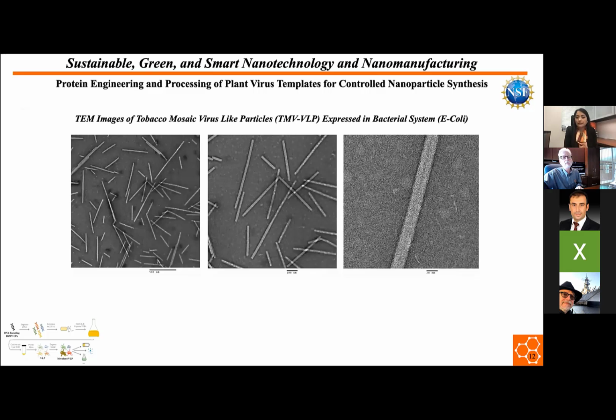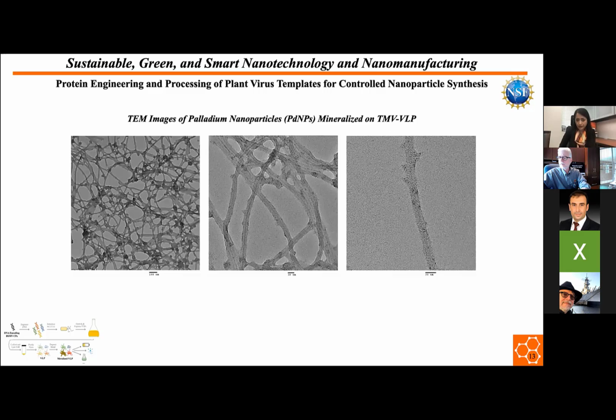I'm going to share some of the results that we got so far about TMV virus-like particles that have been expressed in a bacterial system and purified. As you can see in the TEM image, we got really nice VLP nanostructures without any aggregates or any other structures. And we used these virus-like particles as template for the attachment of palladium nanoparticles. And here are some of the TEM images of palladium nanoparticles mineralized on TMV VLP. As you can see, we got the palladium nanoparticles deposited on the surface of TMV VLP.